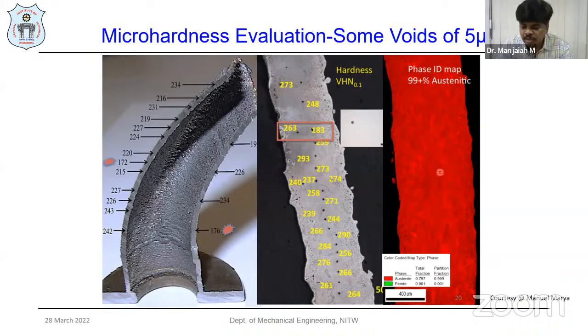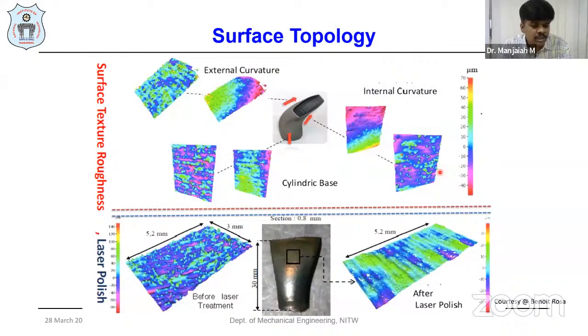This is the phase diagram, which gives us how much percentage of the austenitic phase exists in these stainless steel 316 fabricated components. We also studied the surface topographical aspects in the fabricated components. If you see, this is a component of an air duct. The surface texture shows us how much surface roughness it has on the external surface as well as the internal surface. To minimize this rough surface, we went with laser polishing. If you see before polishing and after polishing, you can see how much minimization can be done with the laser polishing.